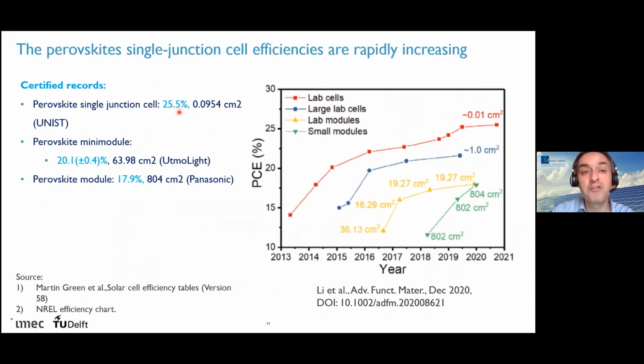This is already very close to the maximum efficiency of silicon. But of course, it's still a relatively new material. All these cell efficiencies are typically measured on very small areas, and if you go to higher areas, the efficiency is still a lot lower. So there is still a lot of research needed in the coming years to make this a better material.